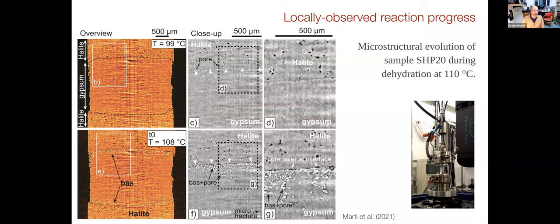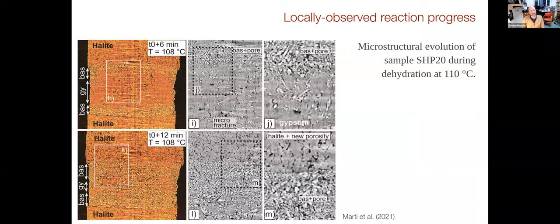If we wait a little longer and follow that reaction, and this is really a matter of minutes at these temperatures, then we can see there's a lot happening in this sample, and we're now resolving those grain scale processes that I pointed out earlier. We see that there's a reaction front developing here, which is slowly migrating downwards and also upwards from the bottom. We see there's obviously fractures emerging, microfractures here. They will be fluid filled at that stage. And there's now needles appearing here.